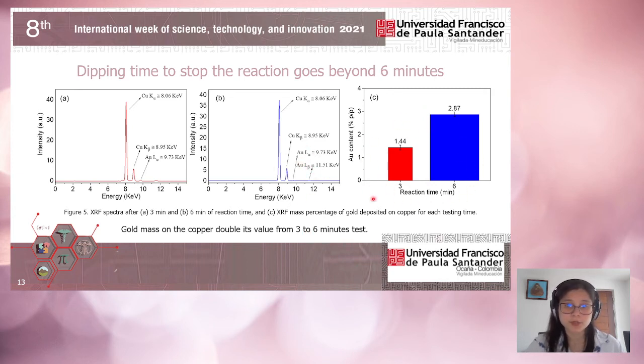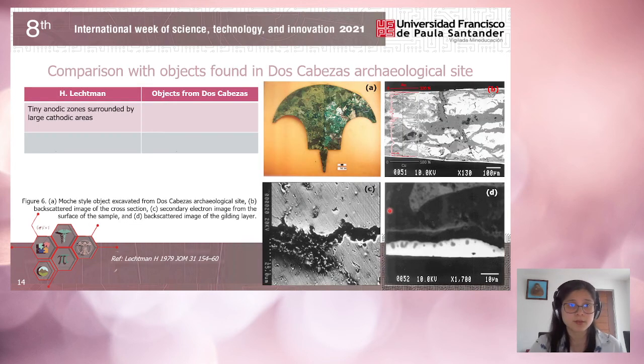The elemental composition showed that the 6-minute sample doubled the content of gold in the 3-minute sample. This means that the reaction could have gone even further. In order to analyze our results better, we compared them to archaeological objects found in the Dos Cabezas archaeological site.